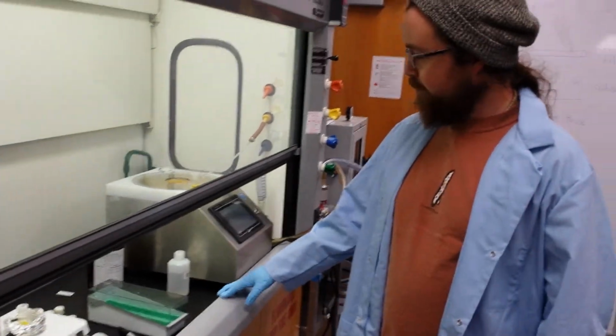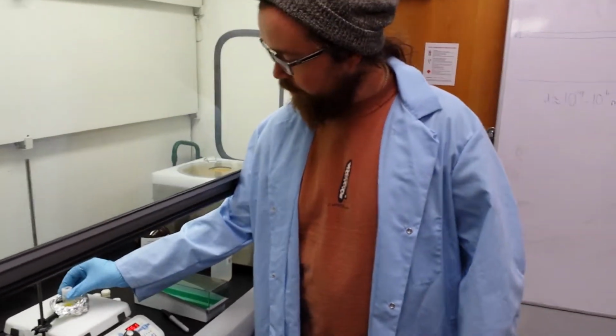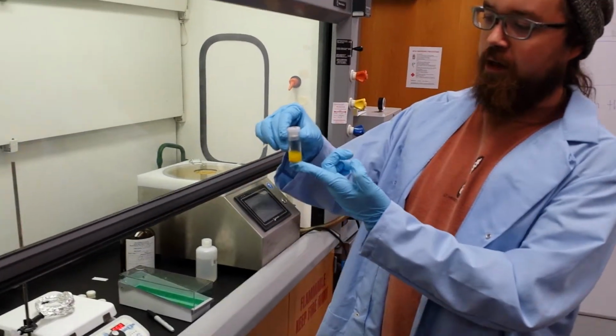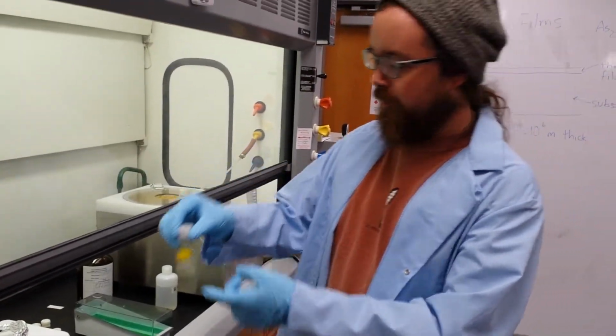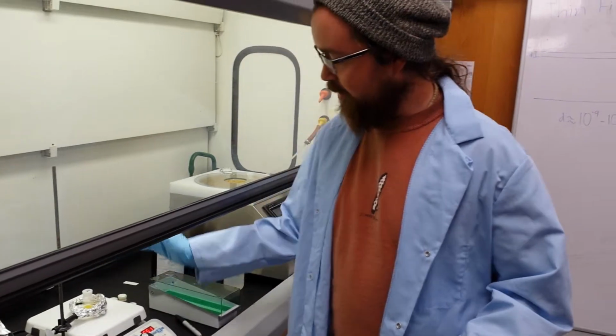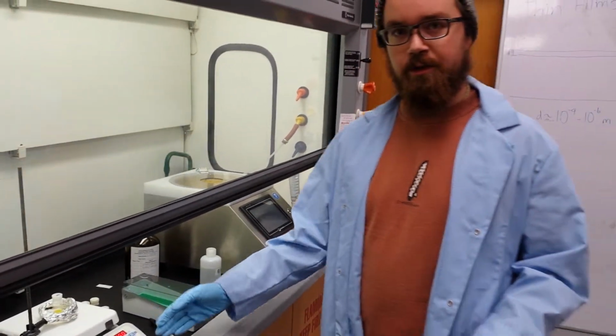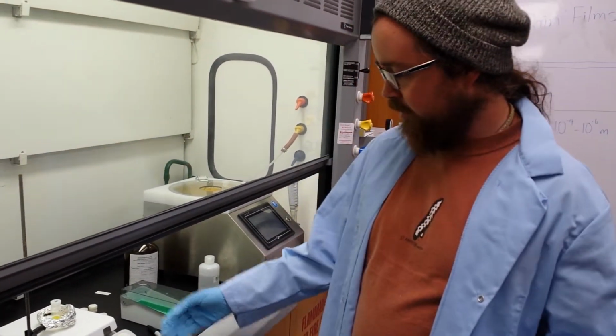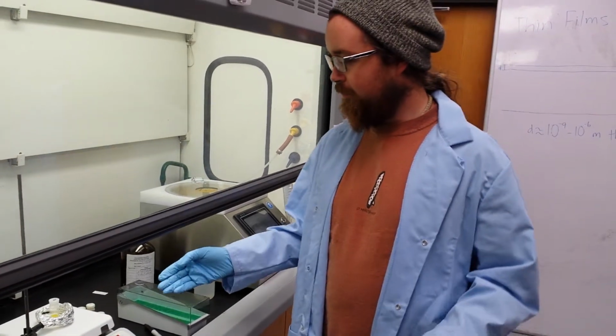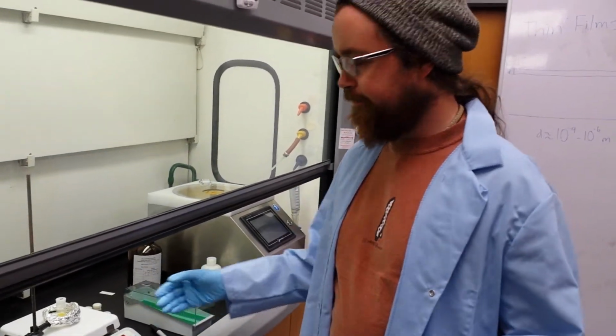So what we actually do is we dissolve the glass here in an organic solvent, and we put a magnetic stirrer in there, and then we place it here onto the hot pad, which has a magnetic stirrer built in. And the stirrer will mix the solution until the glass is fully dissolved, which usually takes about a week.